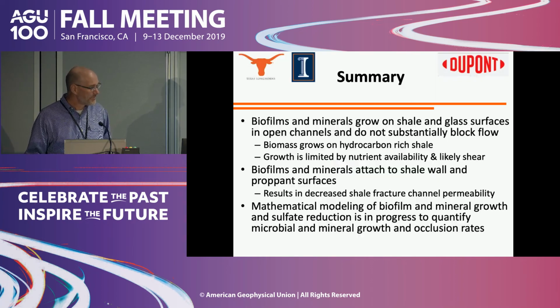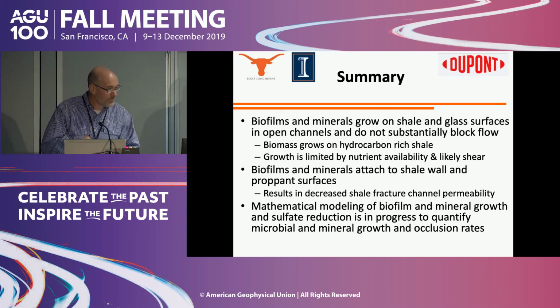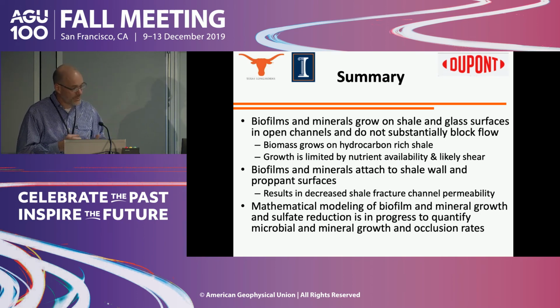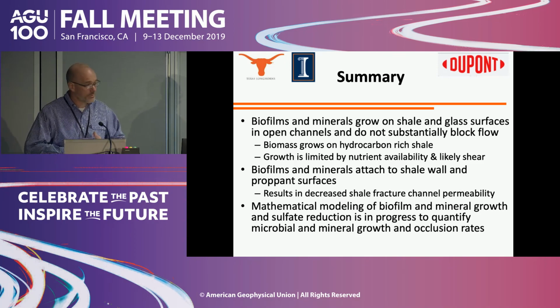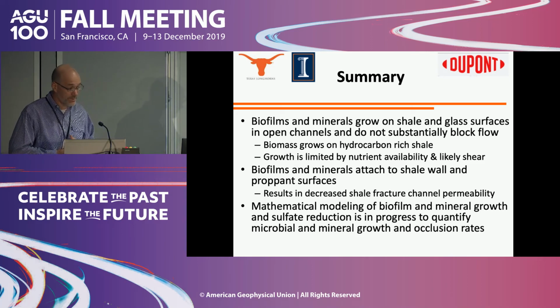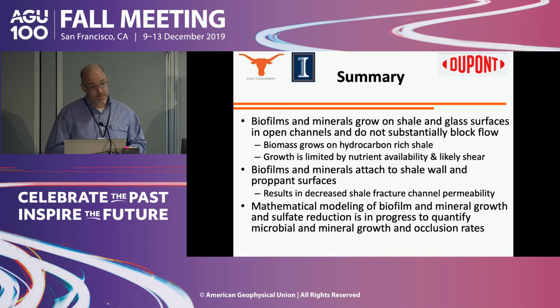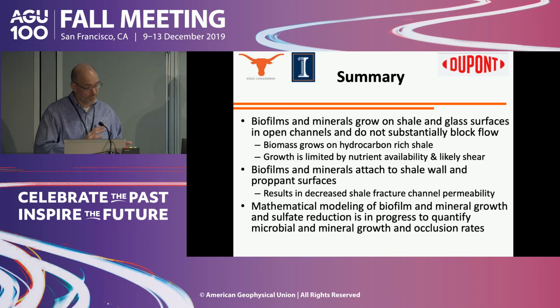Either way, summarizing: biofilms and minerals grow on these shale and glass surfaces in open channels and don't appear to substantially block the flow. Growth is limited by nutrient availability and, in some cases, shear. When we have proppants present, we get a big decrease in the permeability and increase in the pressure drop. We're looking at modeling this to look at the reaction rates, and also at what's leaching out of the shale into the effluent under non-biological and biological growth conditions when we have reducing conditions. And that's all. Thank you.